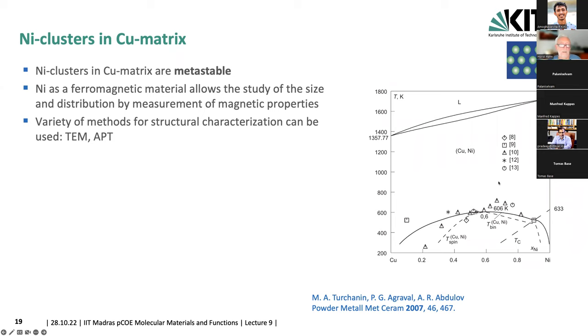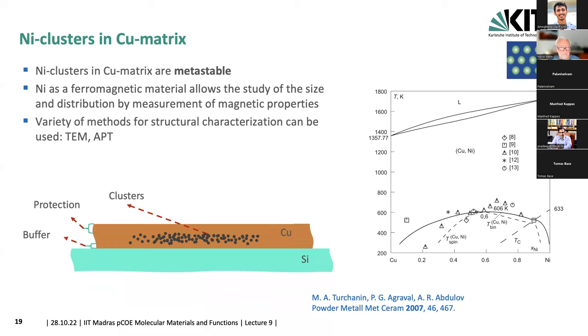So nickel as a ferromagnetic material also allows a study of the size and size distribution by the measurement of magnetic properties. And we have a variety of methods which we use for structural characterization, for example by TEM or by atom probe tomography. So here is a sample configuration. We take an oxidized silicon wafer, we deposit a buffer layer of copper to separate the nickel, which could otherwise react with silicon. We protect it from that. And then we have this cluster-assembled nanocomposite, and then we cover it again with copper, also to prevent reactivity with the environment when we take the sample out.